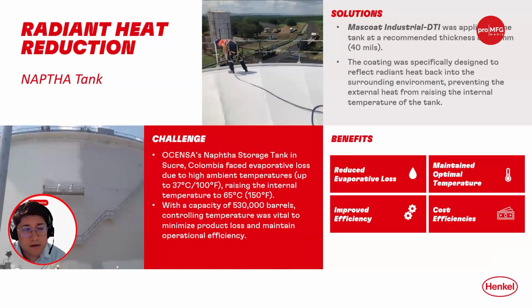Next, please. This is a great example also about our thermal insulation coatings. In this case, in Latin America, we have a naphtha storage tank that was suffering from evaporative losses. This was caused because the atmospheric temperature caused the tanks to raise the internal temperature, and then there were more vapors produced, more material loss, and also in the next phases of the process there were issues because of the changes in the viscosity. So we came in, did the thermal analysis, and we determined that with our Mascoat Industrial DTI solution, applying 1 millimeter thickness on the tank, we were going to be able to reduce the radiant heat, control the external temperature affecting the internal temperature of the tank, and reduce the vapor losses.